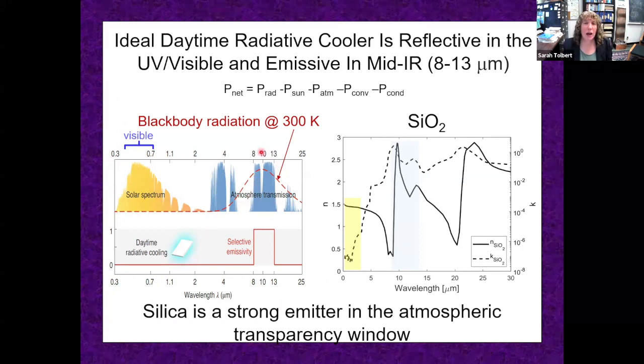Then in the far IR region, there is something called an atmospheric transparency window from 8 to 13 microns, which is where the atmosphere can actually pass IR light. And remarkably, that is also where a black body that is the temperature of the Earth, that is 300 Kelvin, emits. So if you can create a material that has very strong emission in this region, it will emit IR light and cool down. So what's a strong emitter in this atmospheric transparency window? It turns out that silicon dioxide, silica glass, is a super strong emitter.